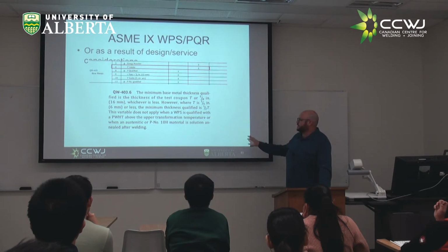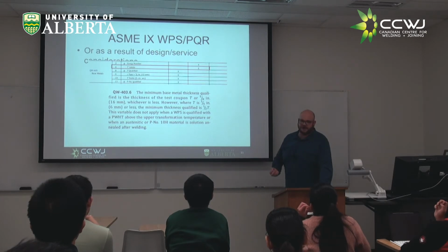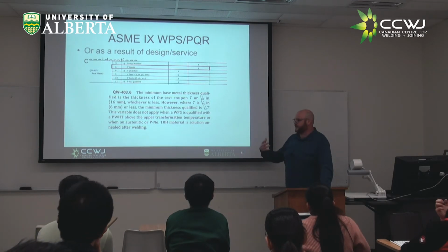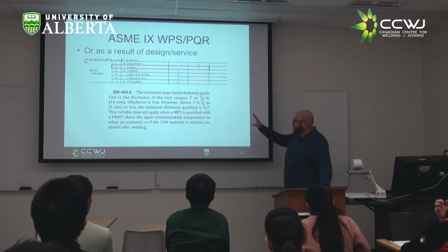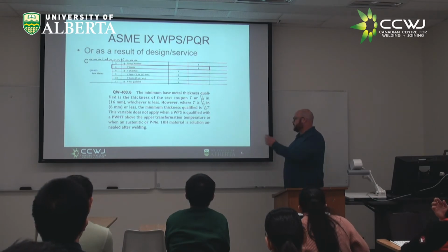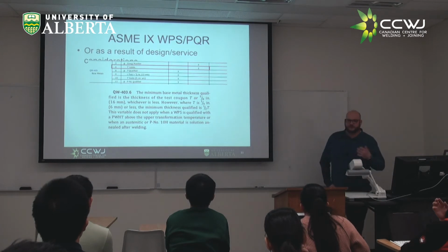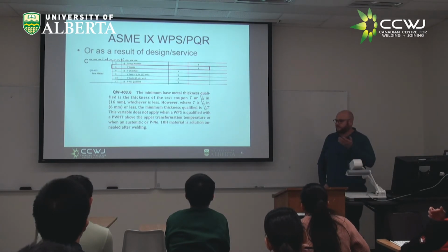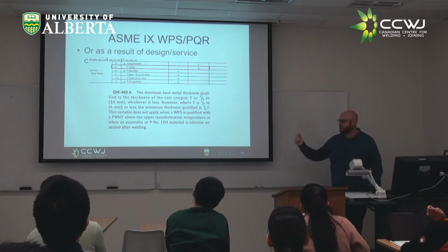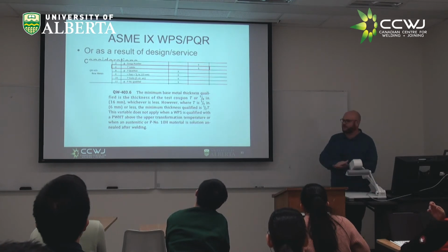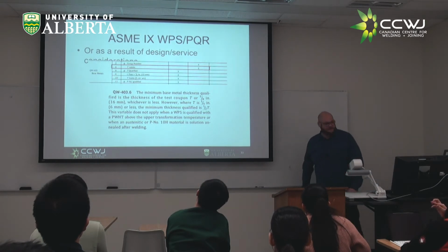The interesting thing that I like about ASME is, as a materials engineer, you can generally go back and find some understanding, or relate it back to base principles. There is an actual scientific basis for this. In this case, it's related to heat input. As we know, heat input has a big effect on your microstructure, which ultimately affects your toughness. So it's just limiting your ranges a little bit tighter, so you can't qualify on something thick that has rapid cooling, put that same amount of heat into a thin coupon, get a lot of grain growth, have a really wide coarse grain heat-affected zone, and all of a sudden you don't get your Charpy properties, right? Make sense? Is everyone with me so far?